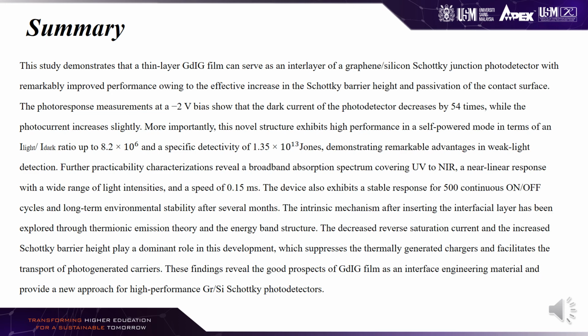The intrinsic mechanism after inserting the interfacial layer has been explored through thermionic emission theory and the energy bandgap structure. The decreased reverse saturation current and the increased Schottky barrier height play a dominant role in this development, which suppress the thermally generated charges and facilitate the transport of photogenerated carriers. These findings reveal the good prospects of gadolinium iron garnet film as an interface engineering material and provide a new approach for high-performance graphene silicon Schottky photodetectors.